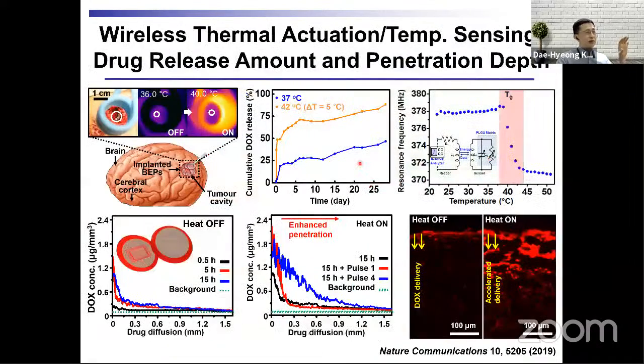After implantation, we can apply an external magnetic field, typically 30 minutes per 2 days. And if we apply the magnetic field, due to Joule heating, the drug release will be accelerated from 25% up to 75%. And also the drug penetration depth can be increased a lot. So without heating, the penetration depth is shallow. However, with heating of 5 degrees Celsius, the penetration depth can be increased much. We can control the temperature increase below 10 degrees Celsius, typically around 5 degrees Celsius, and that could be measured by using the temperature sensor.